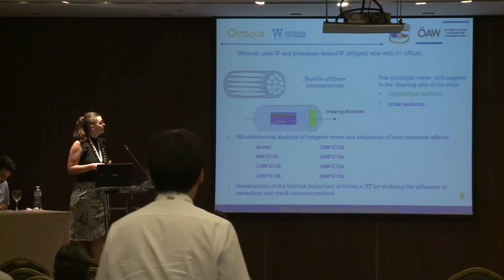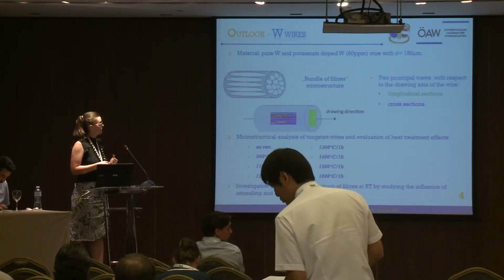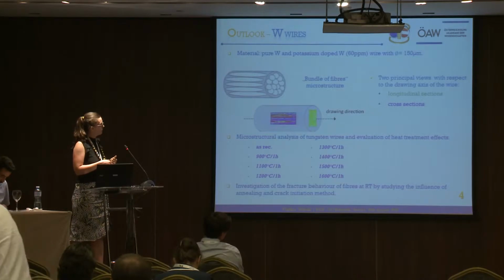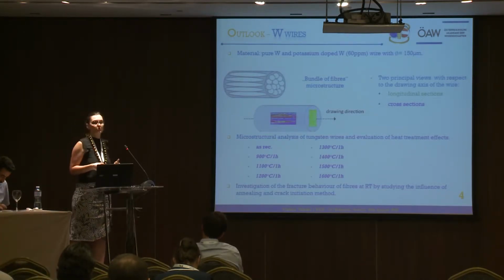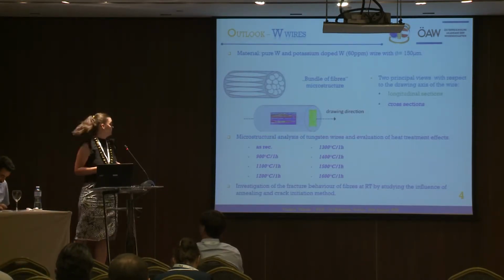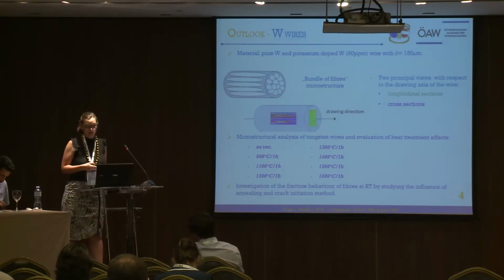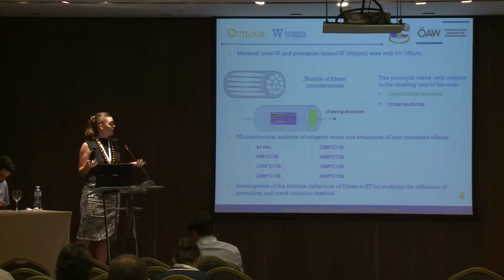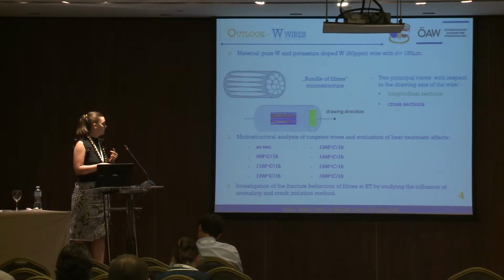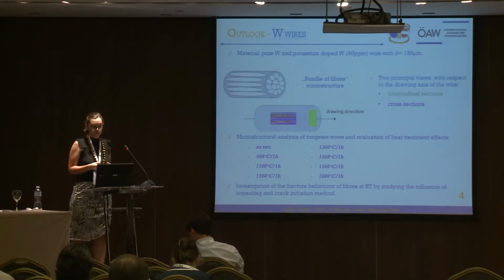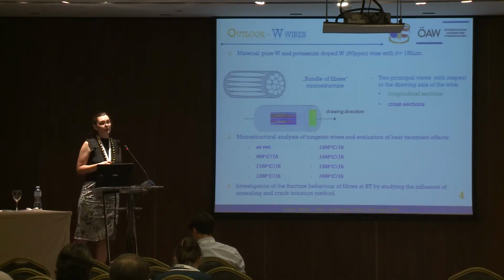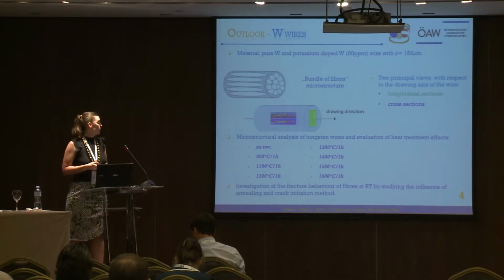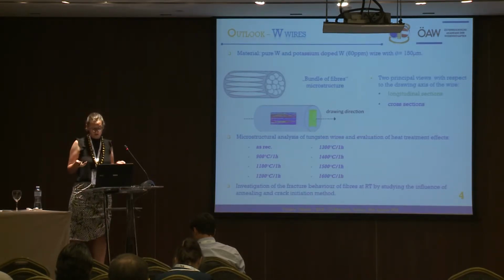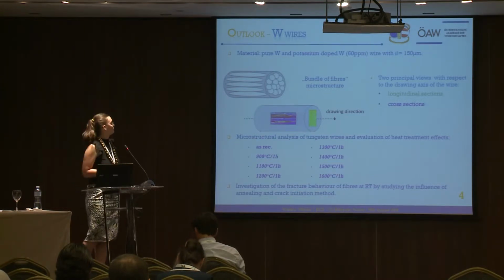The whole microstructural characterization was done in two views. So we were looking at the longitudinal section and the cross sections to get a complete picture of the microstructure. The analysis was done in relation to different heat treatments. Here you can see the temperature range, with the highest temperature of 1600 degrees C. And then all the fracture properties were done at room temperature with two chosen annealing treatments as an addition.